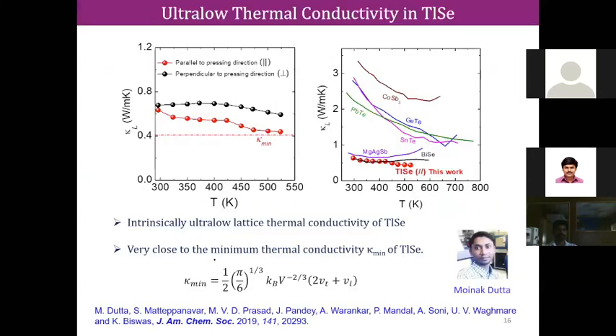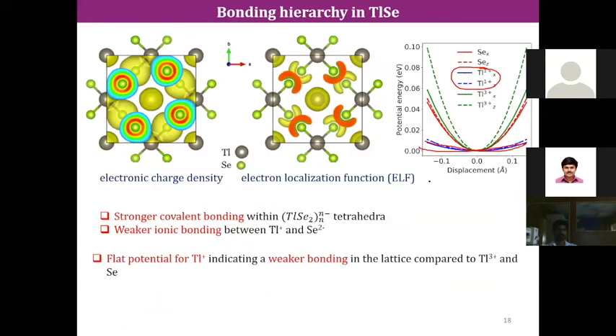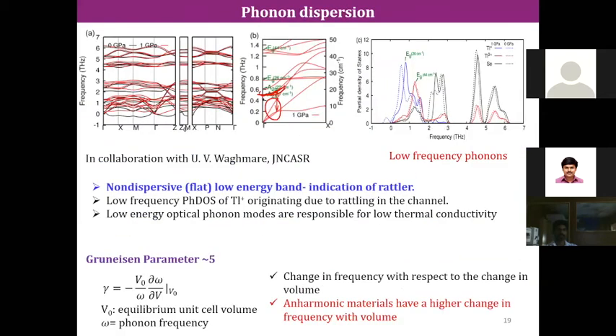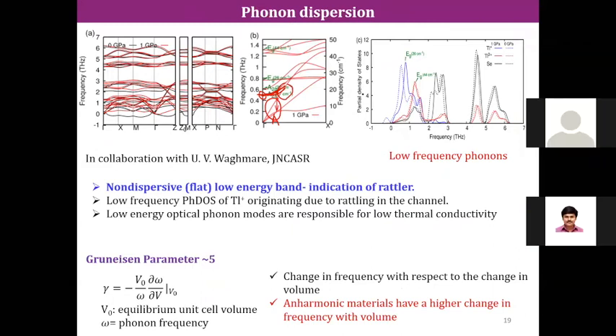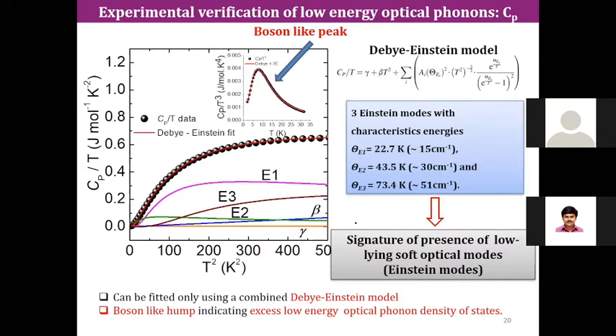Okay. So basically, this is the optical mode, and this is the acoustic mode. So this coupling is happening, and if you do mode analysis by calculating the atom projected phonon modes, you can see these blue low energy optical modes are nothing but coming from the thallium atom. So that gives us a proof of rattling mode. Now this theory is nice, but you have to give experimental evidence of this rattling.